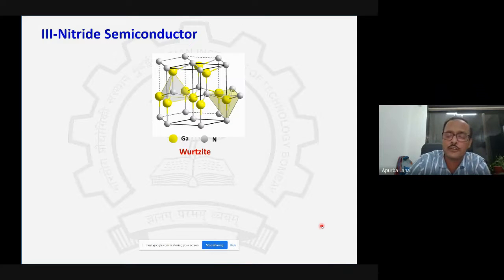If you take a unit cell of gallium nitride, it shows a hexagonal wurtzite structure where the alternate layers are gallium and nitrogen. An interesting thing about this structure is that because gallium and nitrogen have different electronegativity, the structure is unique in its property because it inherently has a polarization, or an electric field built into the crystal itself. That electric field sometimes helps us create a unique device, which I'm going to show, but sometimes it creates obstacles or limitations when you're looking at optoelectronic devices or the light emission from the structures, for example.